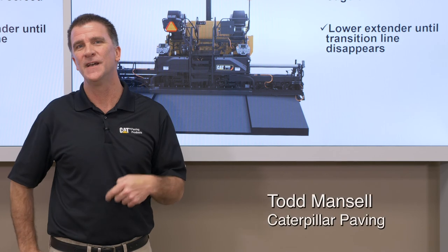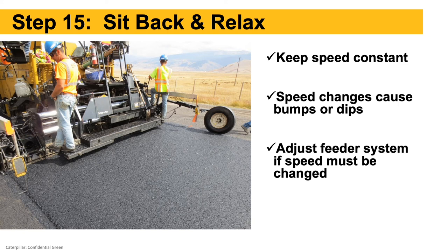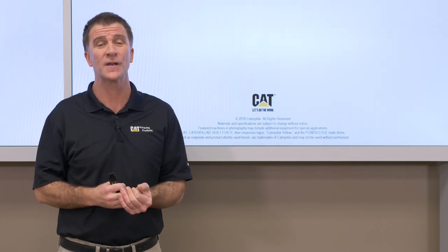Once you've got all that done, just maintain a constant paving speed. Speed changes cause bumps and dips in the mat because head of material changes. So if we change speed, the first thing to think about as paver operator is that we should also be changing the feed system — meaning the conveyors. That's paver operations basics: introduction to the tractor and screed, how they work, and 15 steps to getting a consistent takeoff every time. Thank you.